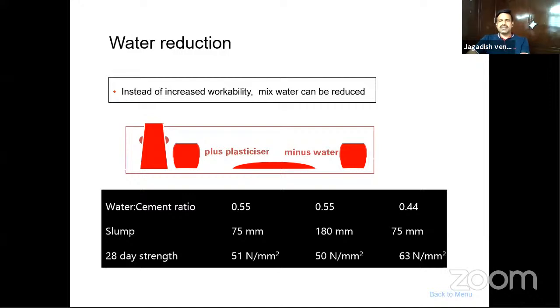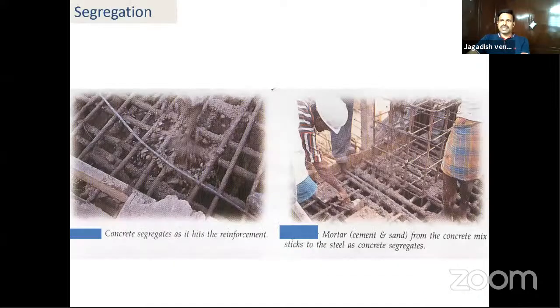In the second case, we have maintained the same slump. By adding chemical admixture, you have reduced the water cement ratio, such that for the reduced water cement ratio, you got more strength, that is 63 MPa from 51 MPa. So by changing the water cement ratio or maintaining the water cement ratio, either you can get the slump or you can get the strength.